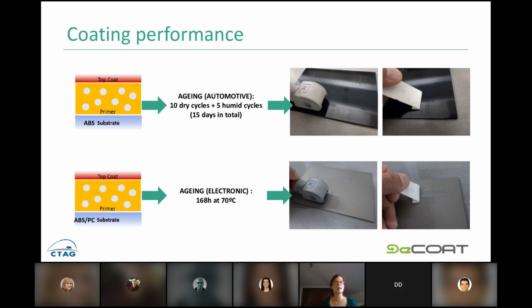So to check that, we make an aging test, very demanding for both automotive use case and electronic use case. We exposed different samples to this aging, and after that, we performed the cross-hatch test to see if the coating is okay and it's still performing well. And the tests are okay in both cases. So it means that the coating developed in the Decode project is able to stand the requirements for both industries, and it's removed only at the end of life of the product.